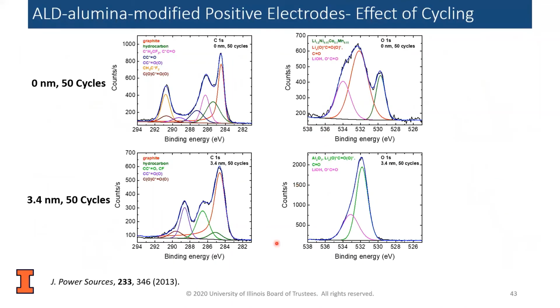So this is just a comparison that here we see the differences between the cycles. We have a lot of carbonate in this case, and in the coated we don't have a lot of carbonate. So in this case, mostly because the nickel is now moving towards the surface of the electrode, we're getting some oxidation or some reduction, I mean, of the carbonate at the surface.